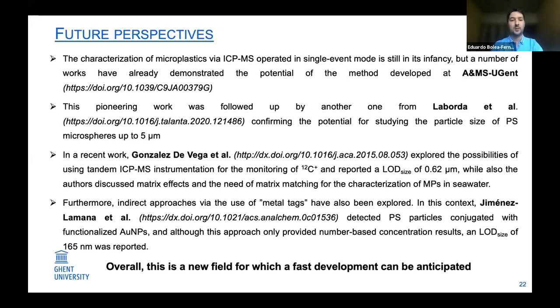Furthermore, I would also like to mention that in addition to some direct approaches, like the ones that I've mentioned up to now, focusing on the monitoring of carbon, also some indirect approaches have been used by using some metal tags. And in this context, Jiménez-Lamana et al. detected polystyrene particles conjugated with functionalized gold nanoparticles. So basically, they monitored gold for the detection of micro and nanoplastics. And although this approach so far only provided number-based concentration, they report a size detection limit of 165 nanometers. So I would like to conclude by saying that overall, this is a new field for which a fast development can already be anticipated.